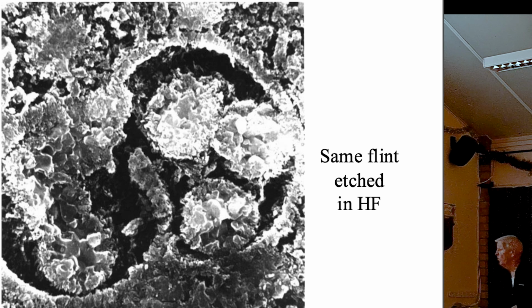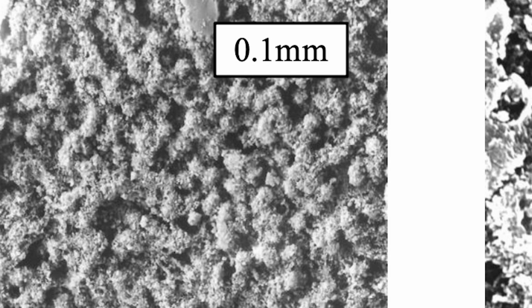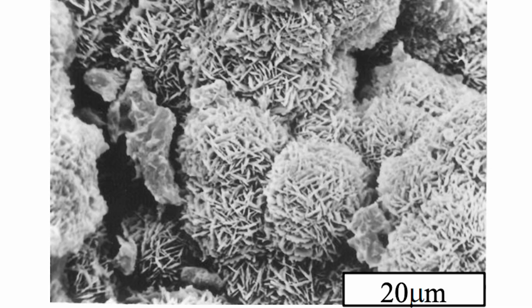Now, fortunately, we know quite a bit about those, because if you back out a bit, you can actually see it's the main component of the flint. But if we go to modern silica-rich sediments, like radiolarites and diatomites, what we find is a lot of these little things which form. And as you can see, these samples over on the left here are exactly the same scale as the ones in flint. And we refer to those as lepispheres.